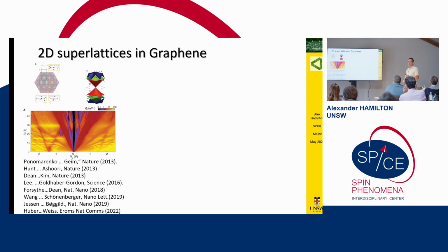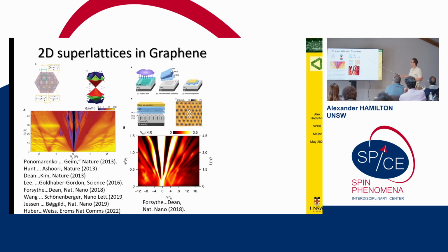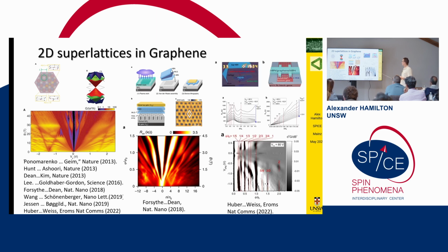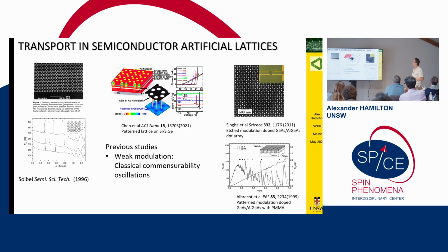What you could try and do is take that graphene and pattern an artificial lattice into it. And so there have been attempts using chemical etching to make artificial lattices inside graphene, or electrostatic gating to make artificial lattices inside graphene. Another way of doing it is to take conventional semiconductors, and on a conventional semiconductor such as gallium arsenide also put an artificial lattice, and then look at the electronic transport of electrons through that artificial lattice.